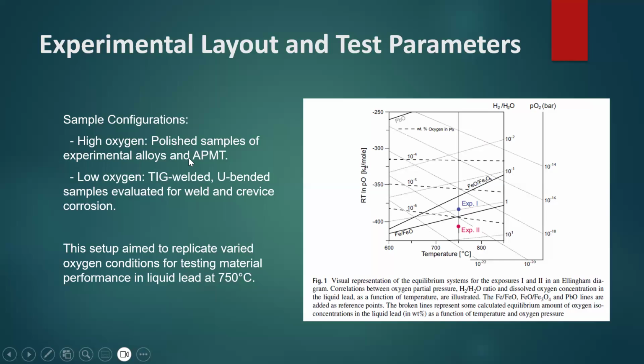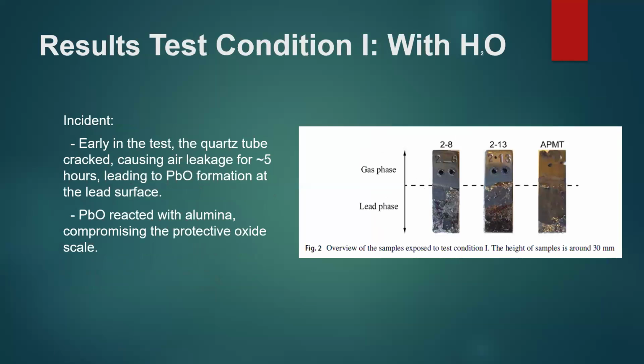Sample configuration: for high oxygen, samples of experimental alloys and APMT; for low oxygen, TIG welded U-bend samples evaluated for crevice corrosion. This setup replicates different oxygen conditions for testing material performance in liquid lead at 750 degrees Celsius.